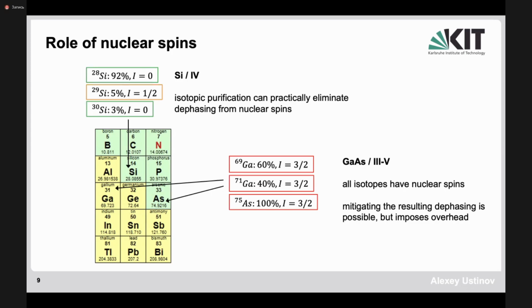So you see all the gallium isotopes, of which there are two major ones used in these gallium arsenide structures, are both magnetic, and they cannot be spin-free states, and they cannot be used as a neutral medium. In contrast, silicon and germanium can be made of really isotope spin-free states, and making isotopically purified silicon is quite a well-established technology in the semiconductor field. And one can have a technique to remove the silicon-29 isotope to completely eliminate dephasing due to the nuclear spins. Therefore, this is a much more promising technique using group 4 semiconductors rather than 3-5 semiconductors for this type of technique due to the role of nuclear spins.